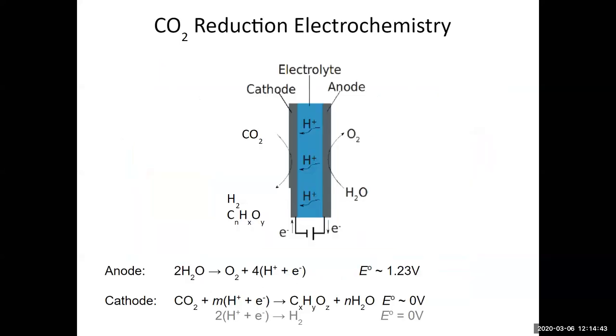So as an example for CO2 electrochemistry, at the anode, we're taking water and we're splitting it to make oxygen. And at the cathode, we want to take CO2 and hydrogenate it or reduce it to something interesting. And specifically, we don't want it to just form a bunch of hydrogen from water splitting. That's a waste of the electricity. The chemistry is quite straightforward, but this is a really challenging problem because selective chemistry is hard. There's a lot of different hydrocarbons that we can make. This is also hard because people have already experimentally brute forced the problem in terms of single cathode composition.